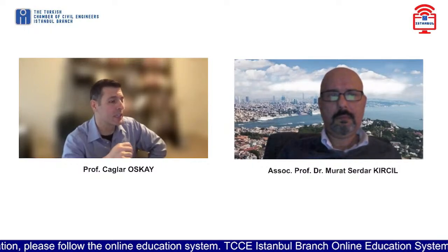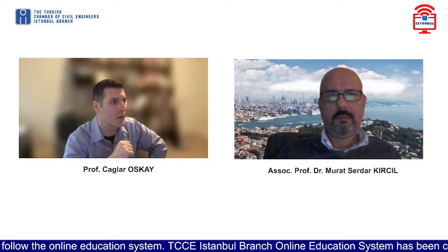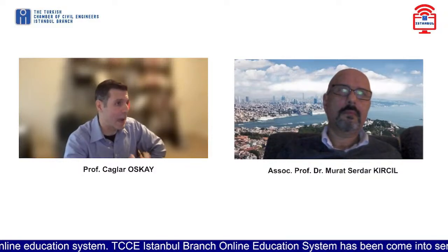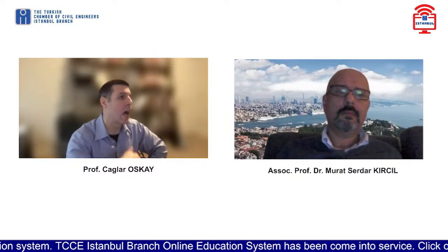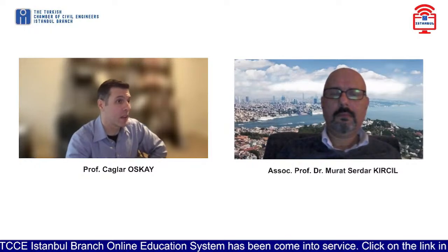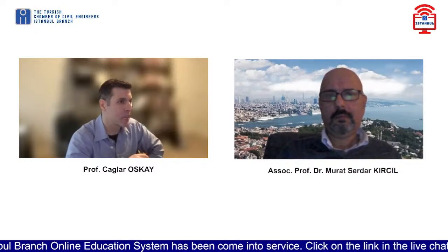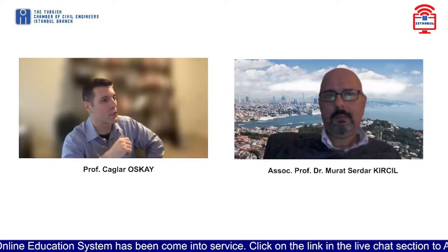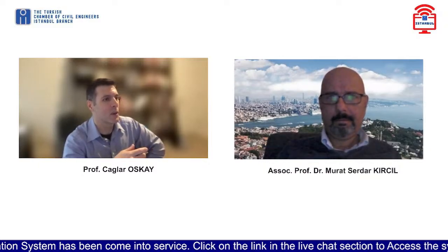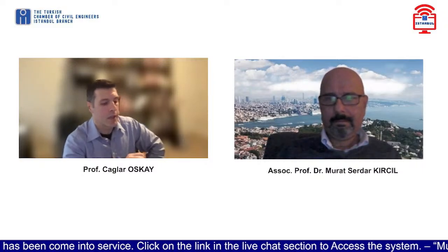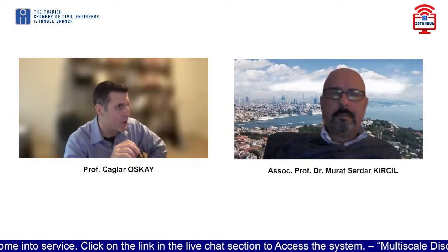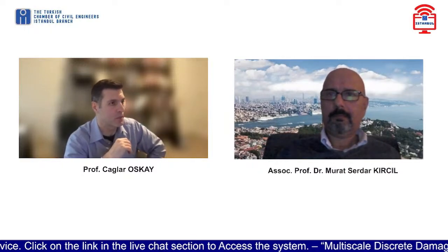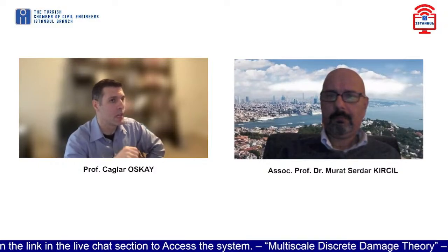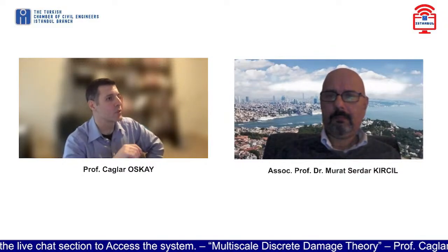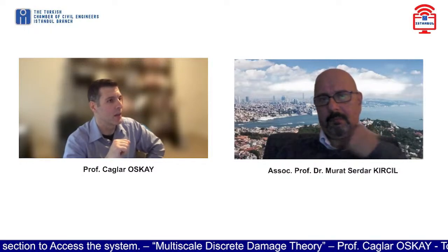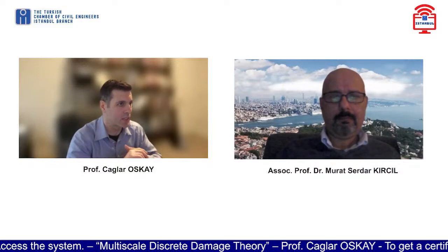We have established models. Maybe you can go into my webpage. They're listed there, that are non-local, that can capture those type of effects using non-local higher order homogenization methods. We go all the way up to 6th or 8th order asymptotic homogenizations to capture those behaviors. We have also recently addressed an interesting question, not in the context of fracture mechanics, but in the context of metamaterials, where we've established a spectral variational multiscale enrichment approach that allows us to capture the wave interactions with the microstructure in a very efficient and effective fashion, even for multiple wave modes when the excited wave modes are multiple. So there are some slight differences depending on the frequency, but those are things that one has to take into account if one wants to focus on those vibrational effects a bit more.